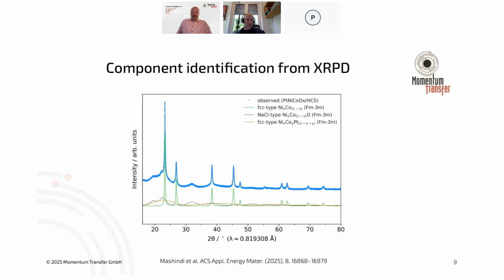Okay. And even with synchrotron diffraction, which I'll talk about in a bit, you get signals that are so good that sometimes you can observe even surface layer effects and things like that. So in this case, this is a layer in nickel metal enriched with platinum, this orange curve. So you can see this is very small crystallite sizes. And then once you've detected all of these things, you've identified all of the fingerprints from these component patterns, you can take these models and quantify the amounts of these materials in your sample to get back a very clear picture of everything that's in there and how much.